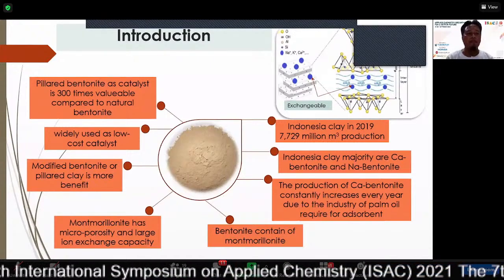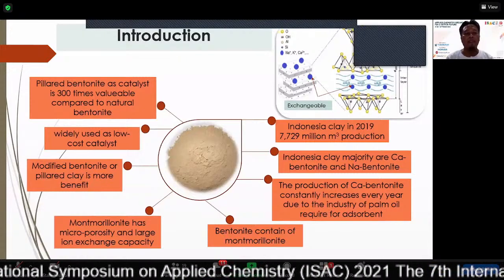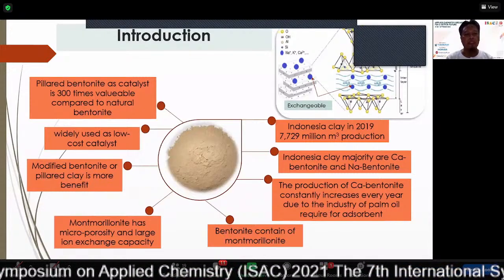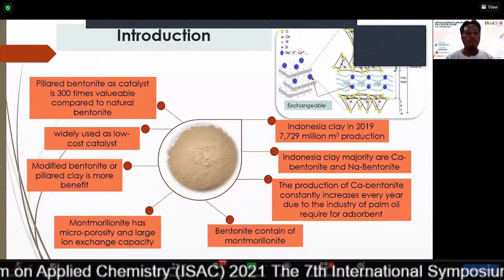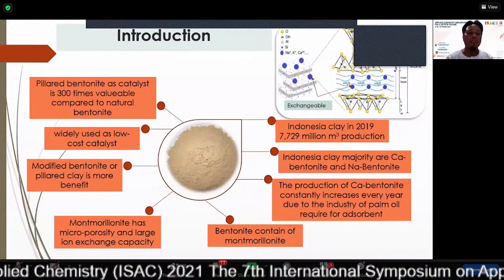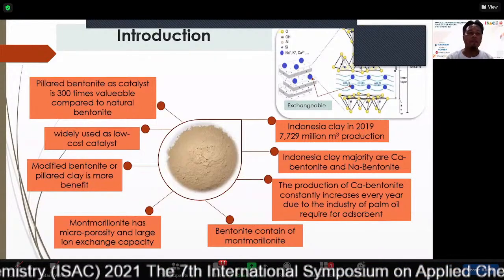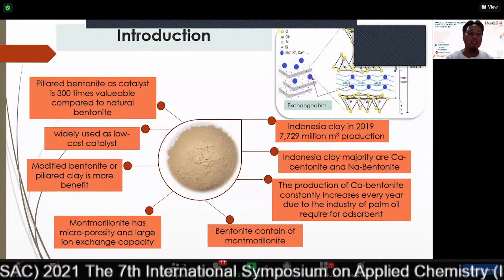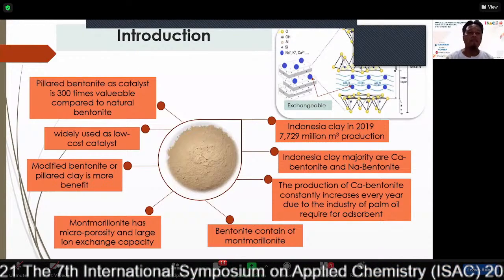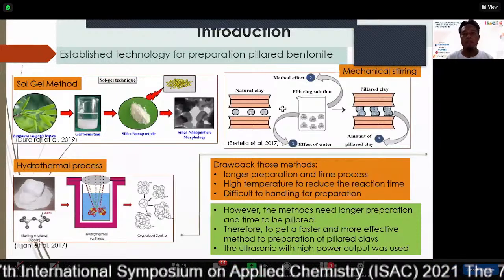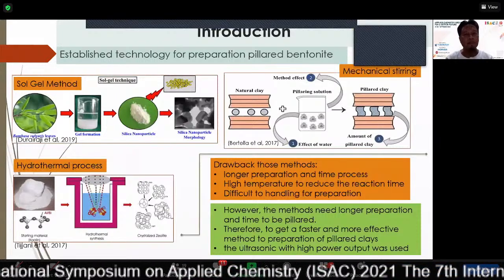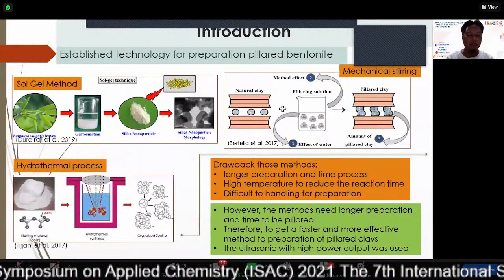Bentonite can be modified into pillared clay, which has more benefits, as it is widely used as a low-cost catalyst. According to the reference, pillared bentonite as a catalyst is 300 times more active compared to natural bentonite. This is the established technology for the preparation of pillared bentonite.